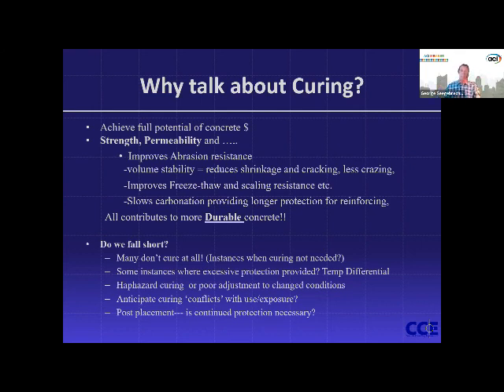And not to dwell too long on this slide, curing, I made up the word conflicts. Don't forget that when you use a curing compound, what's going to happen after the curing period, or as we continue with the rest of the construction, what's scheduled to go on that surface. Curing compound is generally going to act as a debonding agent. So think before you use that, or you're going to be having to add a step of, say, brush blasting that off to make sure that your subsequent treatment will bond. Check with the manufacturer if that is an issue, both with the curing compound and what the scheduled surface application will be.